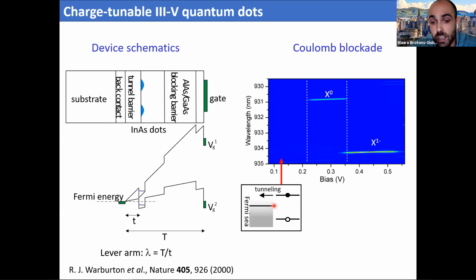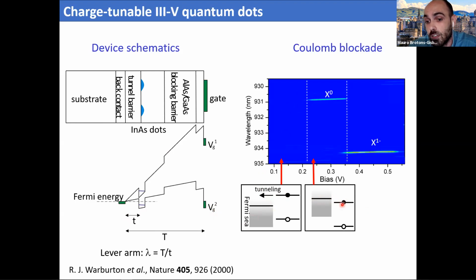But we can change the situation by changing the gate voltage, and we can go to a situation like this, where now our Fermi level lies above the energy level of the confined electron. So basically this electron cannot escape. So we have emission from a neutral exciton, which is formed by one electron and one hole.